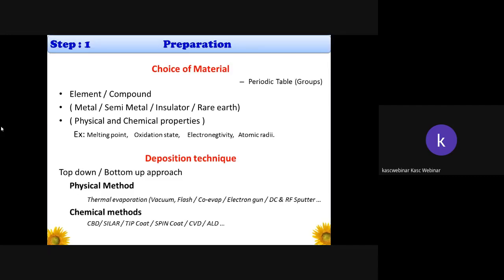Once they have chosen a certain material, either an element or compound, the second step is the deposition technique, which they have to acquire. Either they can choose the top-down method or the bottom-up approach. In the top-down method, the number of materials is limited, and when we go for the physical evaporation method, it's commonly used for thin film preparation, especially thermal evaporation. And again, it can be further classified into different methodologies like vacuum thermal evaporation, flash evaporation, co-evaporation, sequential thermal evaporation, evaporation using an electron gun, and DC sputtering.